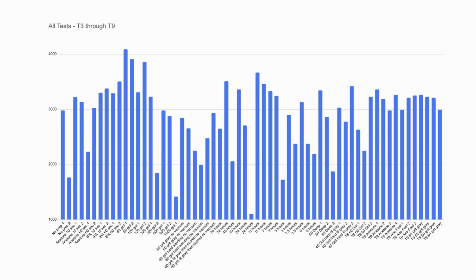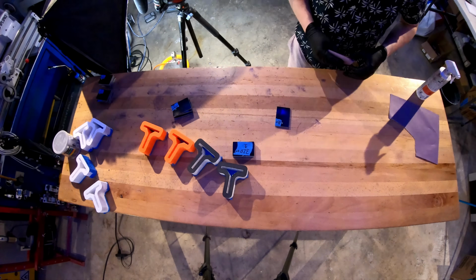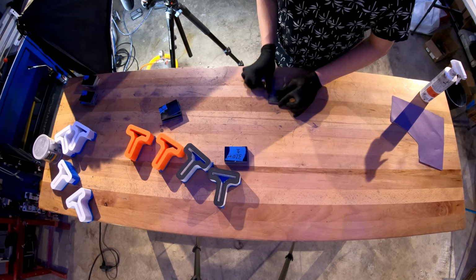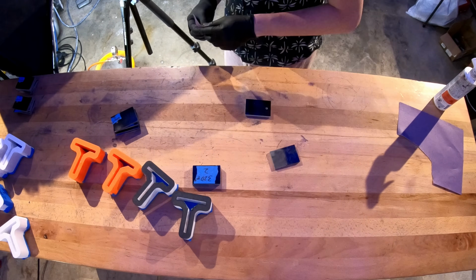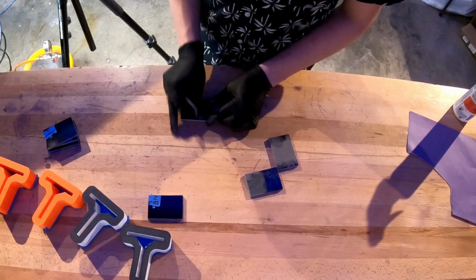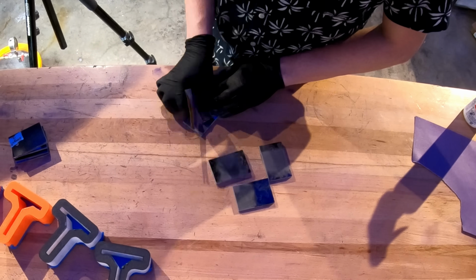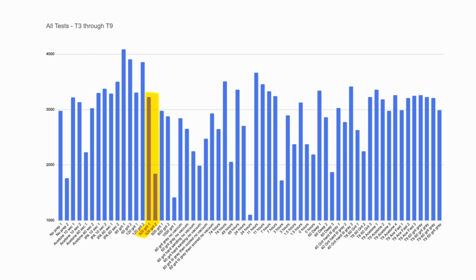So for example, on the 320 grit test, I used the same sandpaper between the first and second coupon. Whatever contamination was picked up by the sandpaper after the first coupon probably made it onto the second, which would explain the low result here. And there are several other examples of sandpaper reuse that have wild differences in their results.